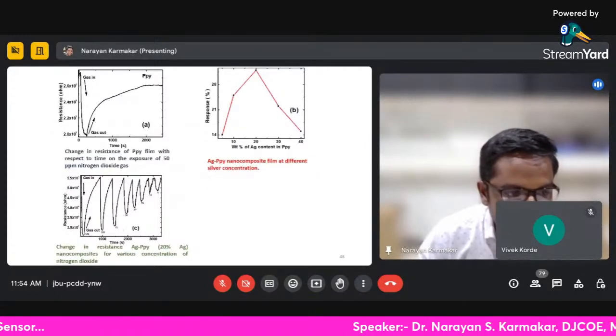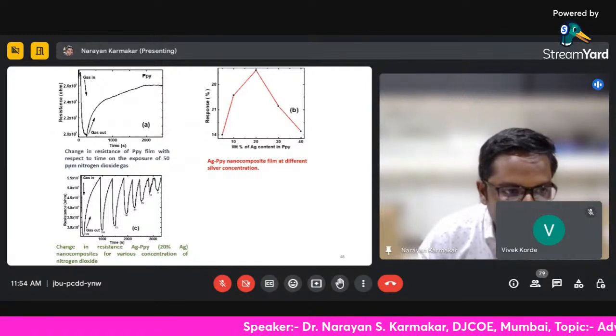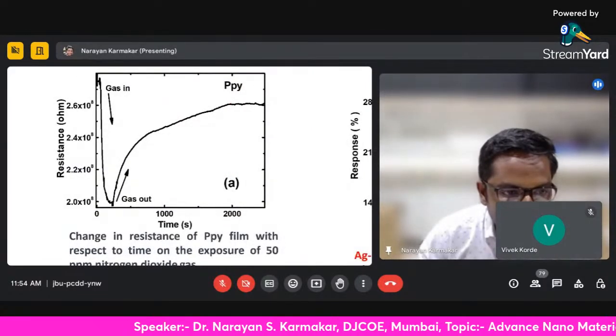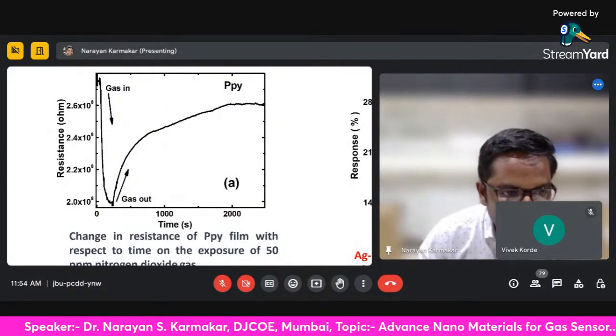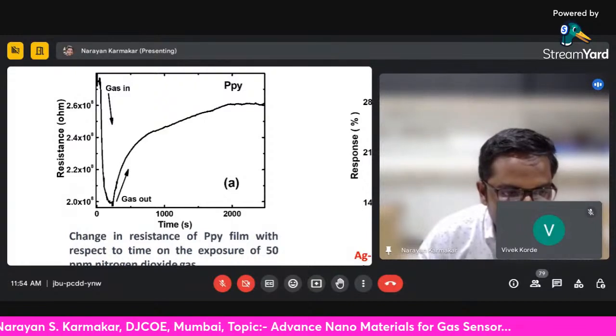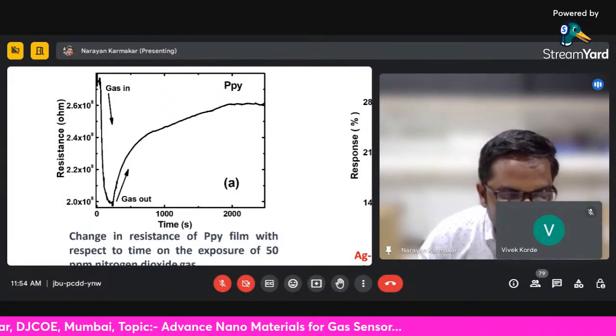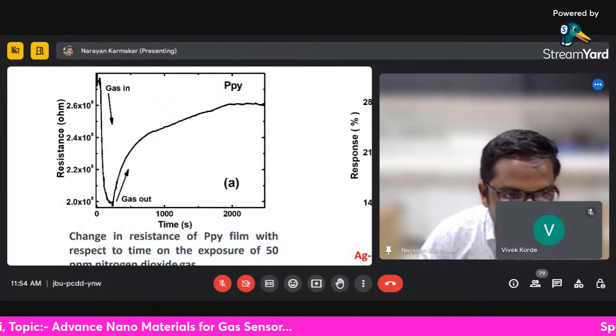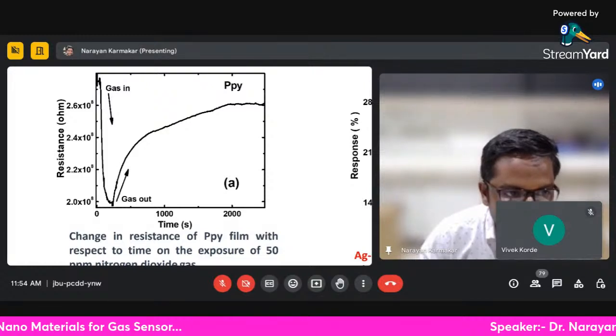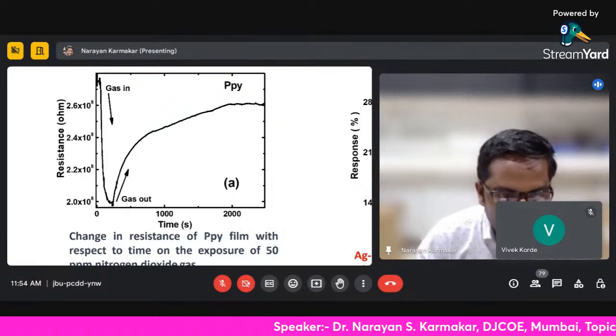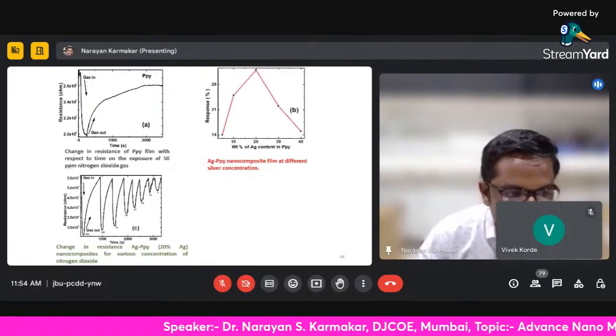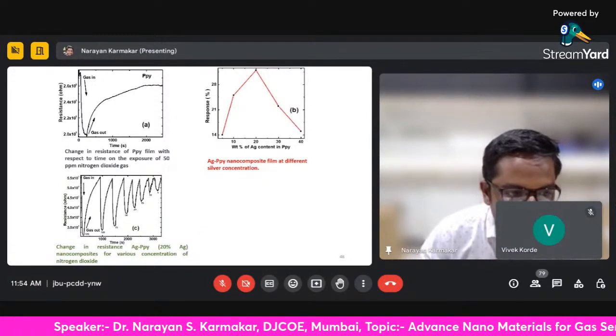So we can look at the results here. For this polypyrrole synthesized using the standard APS polymerization method, it has a good response time, but the recovery time is about 3000 to 4000 seconds. So because of this in situ polymerization...